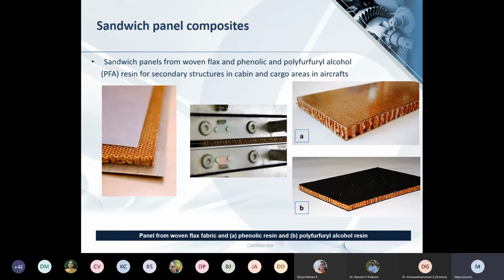And here you can see the sandwich panels that were developed. One of the most important requirements in the aerospace sector, even more important than mechanical strength, is the flammability requirements. It's the flame, smoke, and toxicity requirements. So here we had to treat the flax fibers. Natural fibers, as you would know, are highly flammable. So we had to impart the flax fibers with an environmentally friendly flame retardant treatment. That was the first step. And after treating with FR, these flax fabrics were then coated with the phenolic resin.